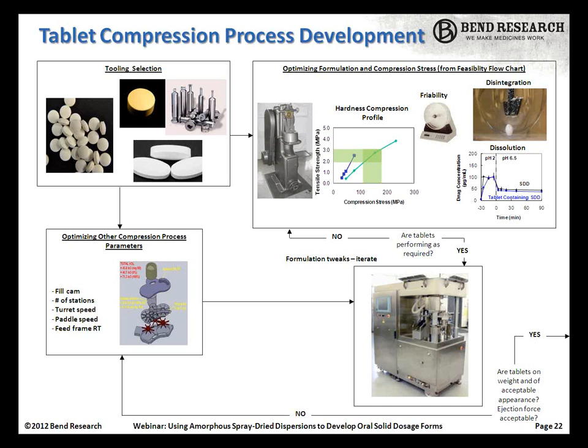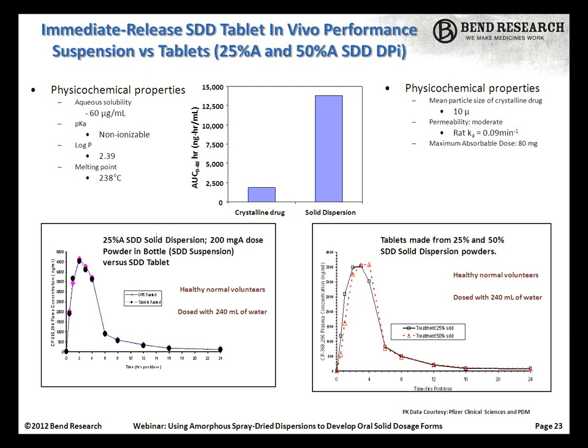Again, our primary metric here for performance is this two-stage dissolution that's shown under the dissolution graph there, the flask. And we generally are always comparing this to a suspension, as Chris mentioned. The reason we do that is, while that sounds like kind of a lofty goal, that is our goal, to achieve the performance of an immediate release tablet that's similar to a suspension of the native SDD particles. So on this graph, I'm showing some data that we can present publicly here.